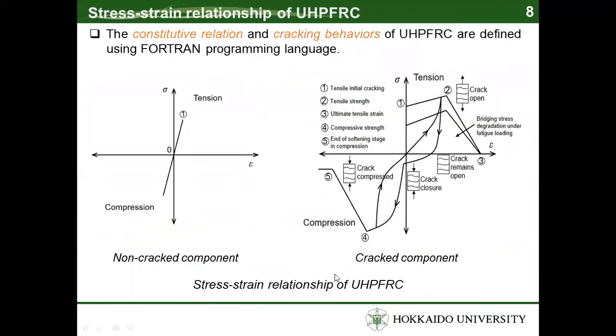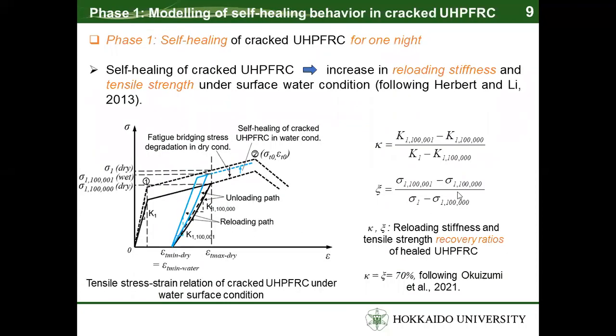Stress-strain relationship of UHPFRC is shown in these figures, which is decomposed into non-crack component and crack component. In the first phase of material model, the self-healing of cracked UHPFRC in terms of increase in reloading stiffness and tensile strength under surface water conditions is considered, and the recovery ratio is chosen as 70% in this analysis, following the results of Okuzumi et al.